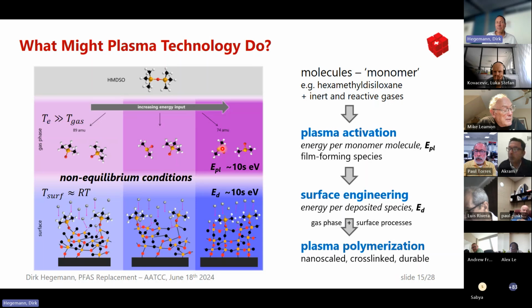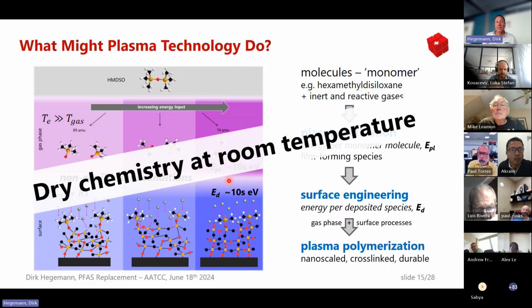That is different from wet chemical approaches, since it's indeed growing layer by layer. It gets cross-linked. It can give a very good adhesion on different kinds of substrate material, and due to the cross-linking, you get a high durability. The interesting aspect is you have hot electrons that supply the energy in the plasma, but the gas temperature stays close to room temperature. Nevertheless, you have energies on the order of tens of eV, both in the gas phase and at the surface, finally to do chemistry, and this is dry chemistry at room temperature, so from the vapor phase.